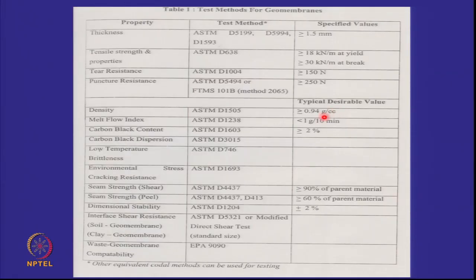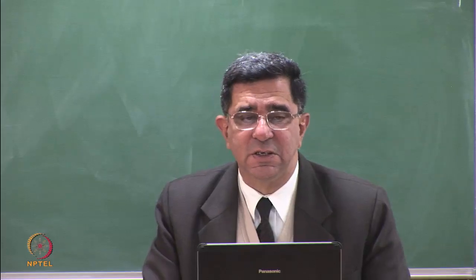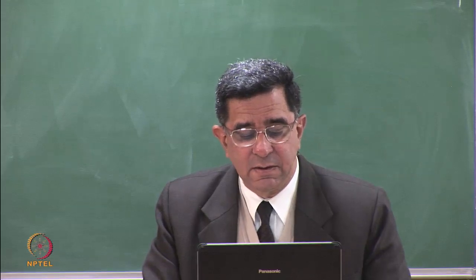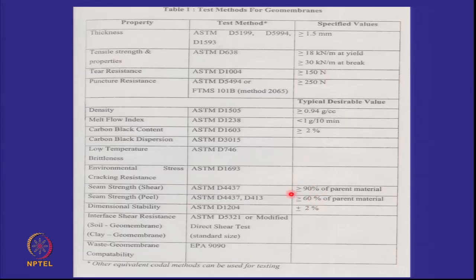It will normally have a density of the order of 0.94 grams per cc, carbon content must be more than 2%, and seam strength must be greater than 90% of the original material. This is a requirement. Seam strength in shear and seam strength in peel, which is totally different, should be 60% of the parent material, and we'll have a look at this later. So there's a full gamut of tests which the geomembrane must meet.